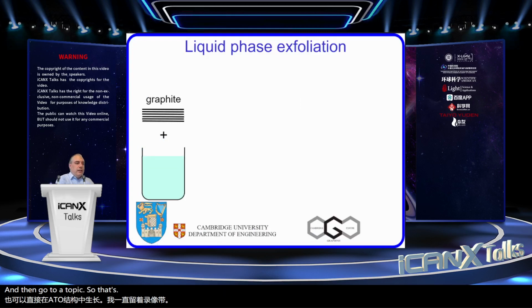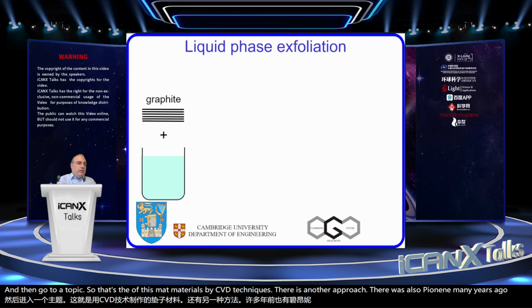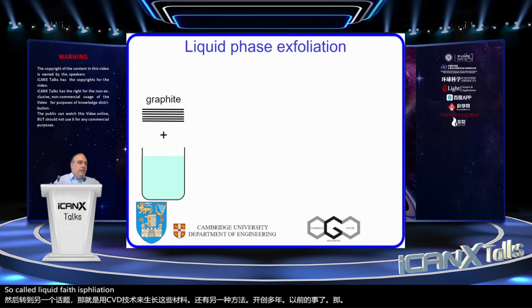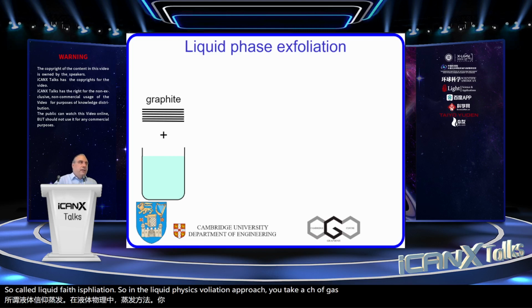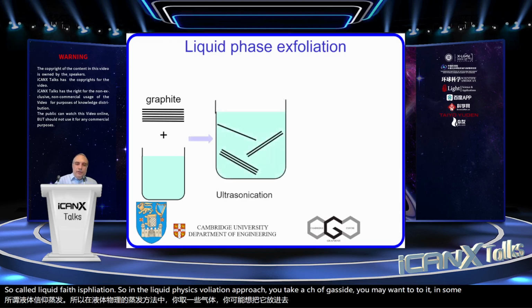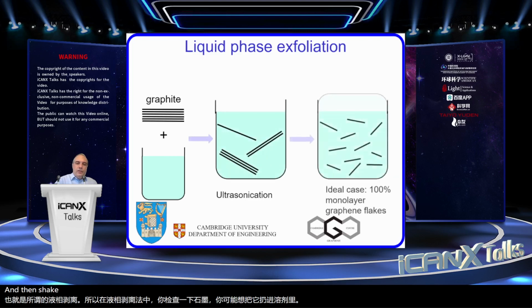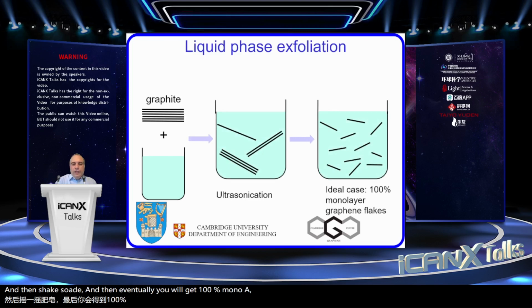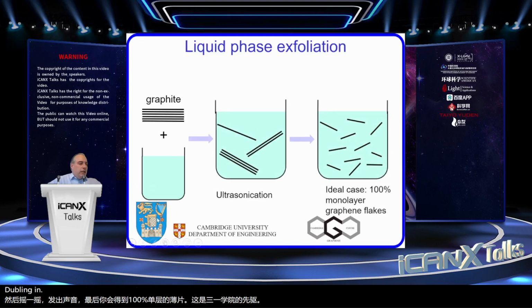So that's the growth of these materials by CVD techniques. There is another approach that was also pioneered many years ago, the so-called liquid phase exfoliation. In the liquid phase exfoliation approach, you take a chunk of graphite, you throw it in some solvent, and then shake or sonicate, and then eventually you will get monolayer flakes. This was pioneered at Trinity College, Dublin, in collaboration with us in Cambridge in 2008.